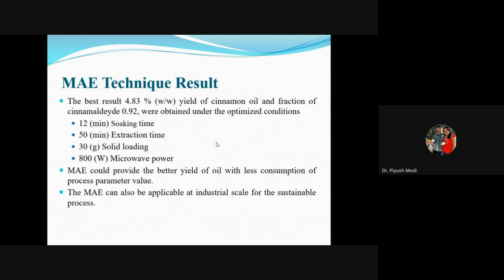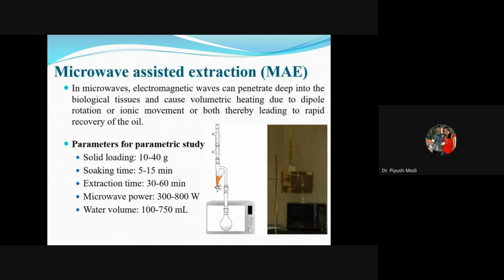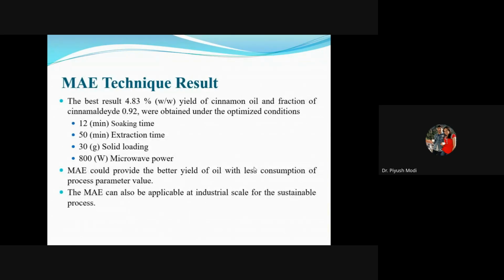In that we get a result of 4.83. I also add one thing: you should not increase the water volume in particular, because if you increase it, your plant material comes out of the flask, as the temperature rises rapidly. In just 1 minute the temperature can rise up to 100 degrees. So we also optimized the water volume here.